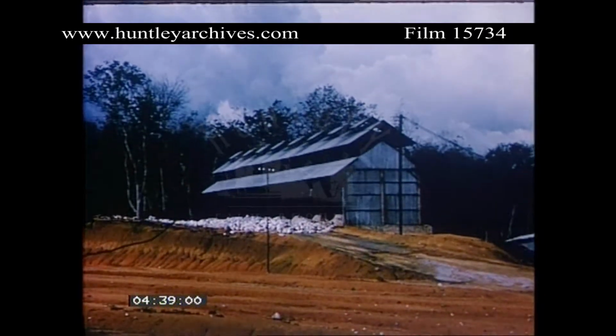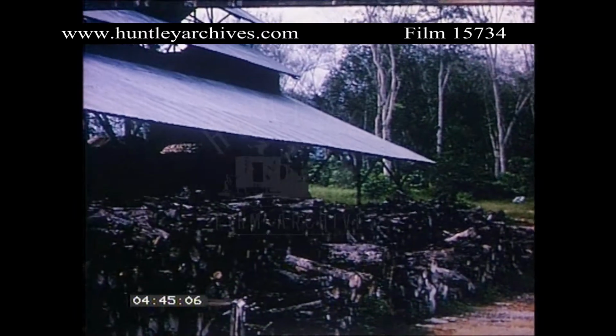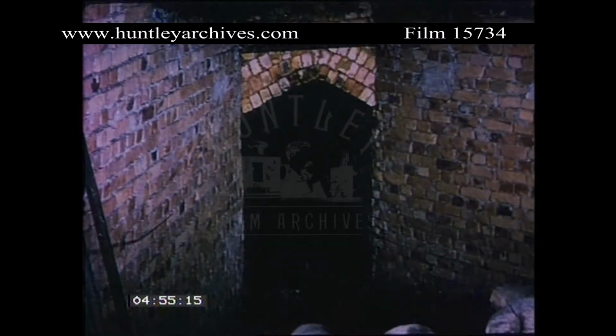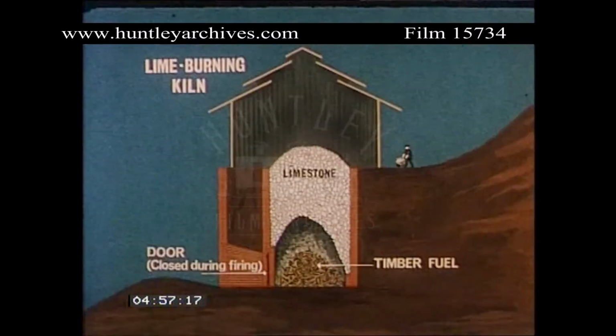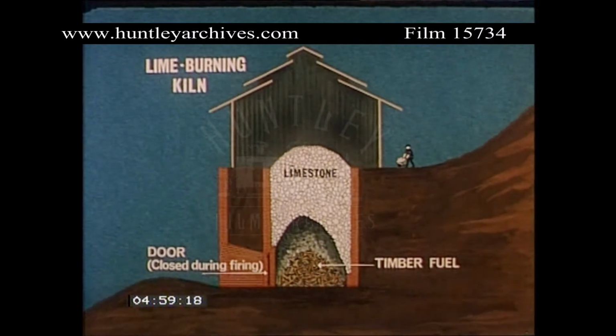The contractor decided to make his own lime, bringing limestone from a quarry 25 miles away and using felled rubber trees as fuel. 6 11-foot diameter brick-lined kilns, 14 foot deep, were constructed on a steeply sloping site, giving access to the top for loading and to the bottom for fueling and removal of lime. The burning was carried out in the traditional Chinese manner.